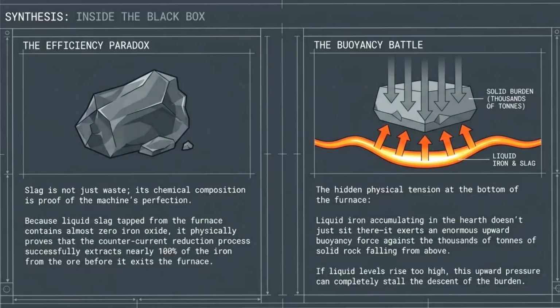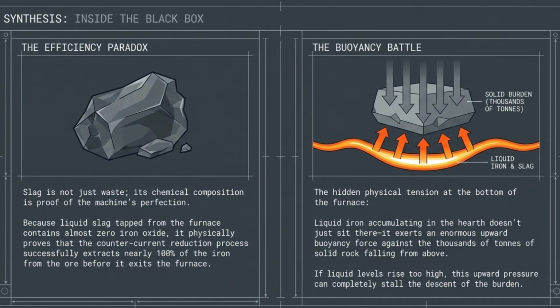As the iron sinks deeper and temperatures climb past 1,200 degrees, it absorbs carbon from the coke, which lowers its melting point. It liquefies. Droplets trickle down through the coke bed and pool at the very base, an area called the hearth. The liquid slag, all the impurities drawn out by the limestone, floats on top of the denser iron. They separate naturally, like oil and water.